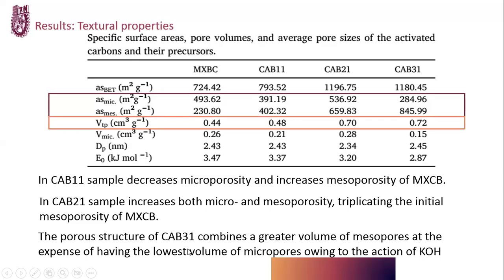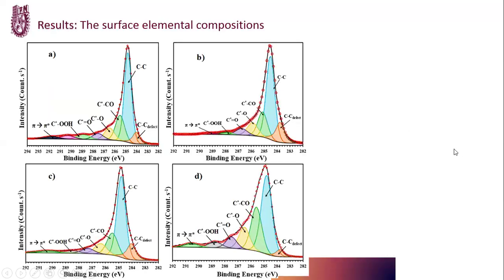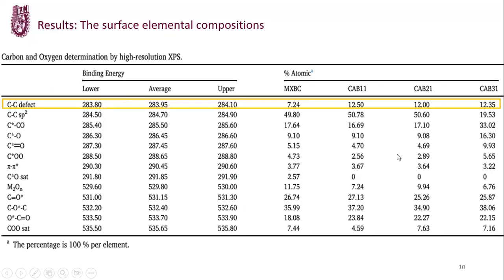Besides, the total pore volume clearly increases with the activation methodology proposed. In this slide, we can see the XPS high resolution spectra of carbon 1s of the four materials, which let us appreciate the presence of several functional groups that are quantified in this table.